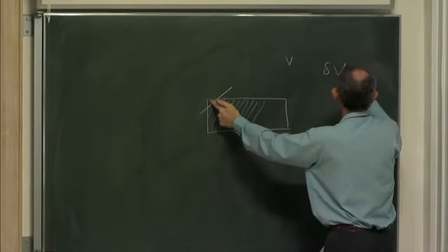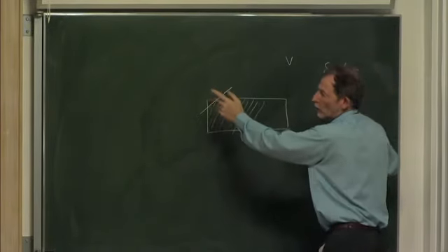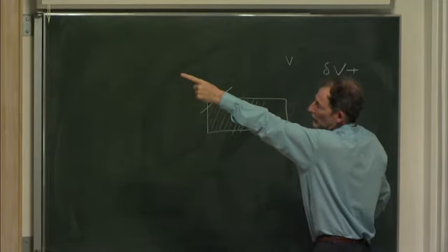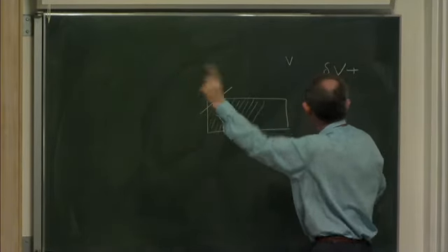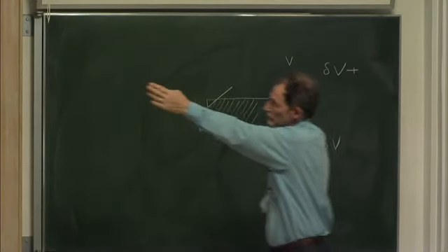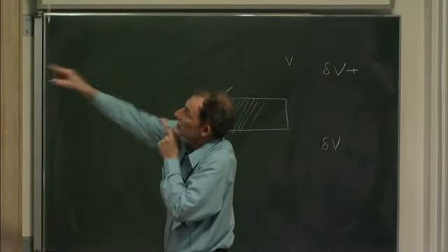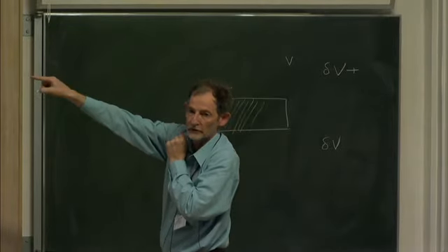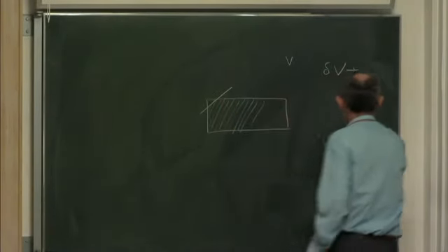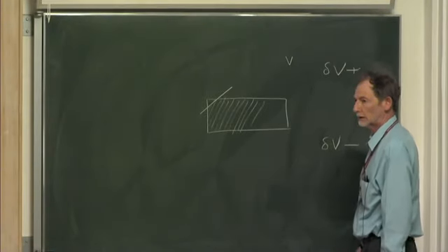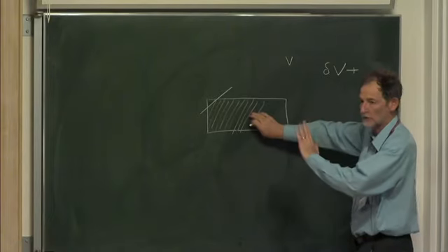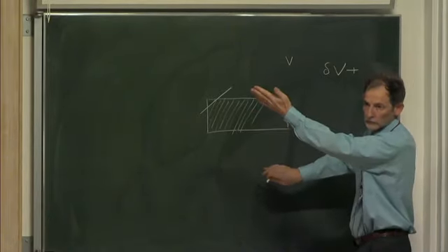So it's plus something. That's the loss of energy. Whereas in this case, you again drop down by delta V because you've reduced the energy. You've got that region where there's the austenite, but now you've got to introduce new interfaces to match onto the martensite. So now I have minus something. That suggests that it's easier to nucleate things in this case than it is in this case.